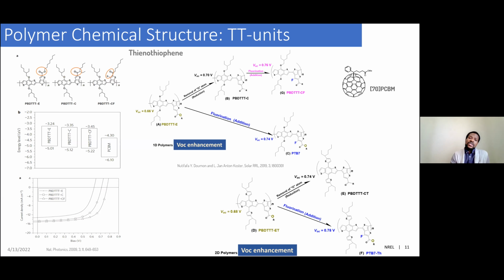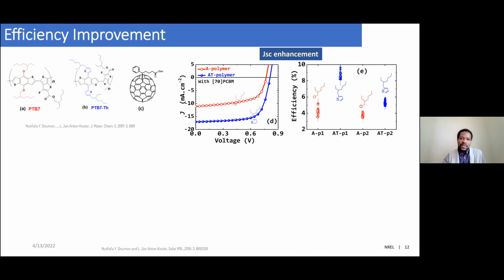And mostly we observe that anything you want to see in the device can already be observed over 2 hours. So though we made this measurement over 8 hours, we decided to stop at 2 hours, based on our limitation, where we already observe changes that we can really study in detail. So we begin with the red and the blue polymer. And as you can see, truly we have increased the current density as we move from the red to the blue. And here you can see 2 more examples of how it affects the efficiency.